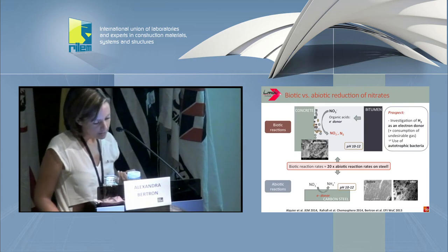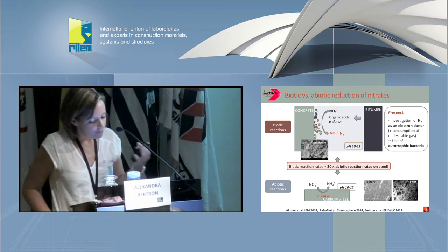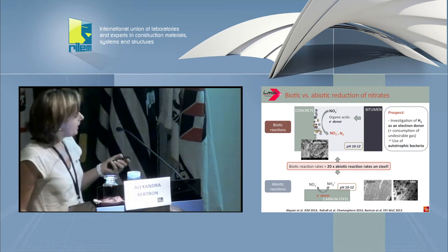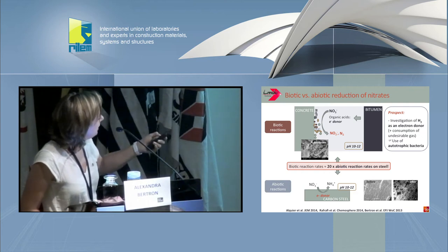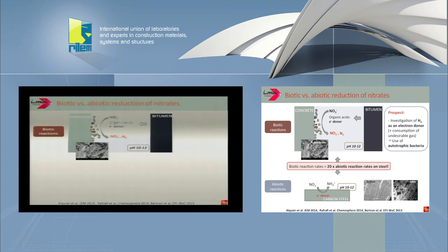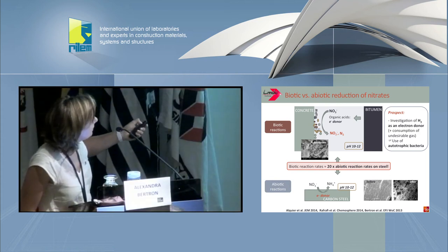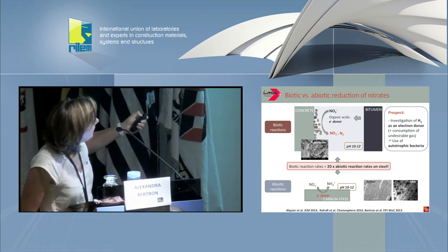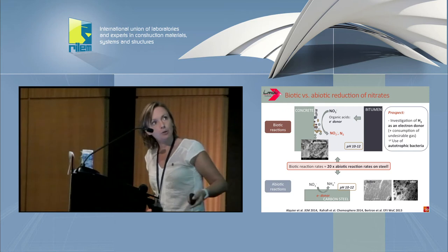Just to make a final scheme to summarize everything, regarding the biotic reactions, at the surface of concrete, a biofilm will be able to develop with alkalophilic denitrifying bacteria, for example. They will be able to reduce nitrates into nitrites and nitrogen using organic acids released by bitumen, which will be the electron donor, in very alkaline conditions.